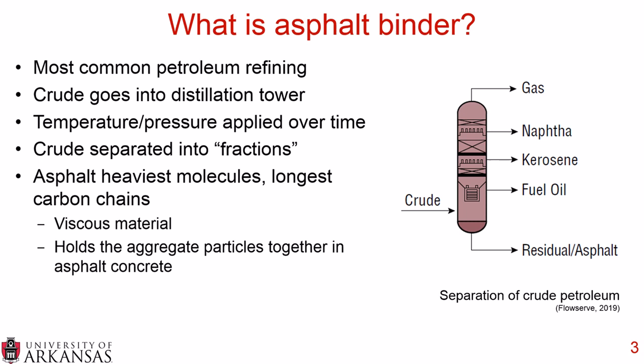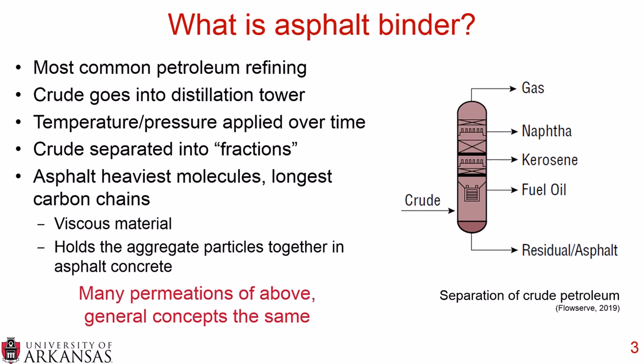Asphalt sits at the bottom because it has the heaviest molecules and the longest carbon chains — it's a very viscous material. In pavement applications and roofing applications, it holds aggregate particles together. For roadway applications specifically, it's a very thin film of asphalt binder on aggregates, which we call asphalt concrete. Different permutations of the petroleum refining process exist, but the general concepts involve time, pressure, temperature, and the separation of different products within petroleum.